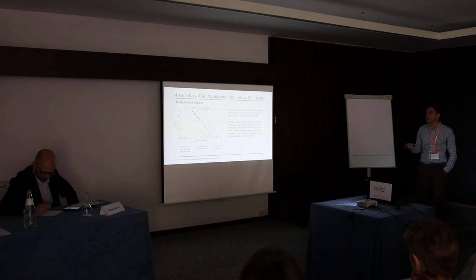If we focus a bit more, we can see that we don't have exact matching, as we expected. For example, these are experimental, so the rounded ones are experimental. We don't have exact matching, which is acceptable. And if we focus on the prediction, on the actual tests, the 2 samples, we can see that we have quite a good agreement.